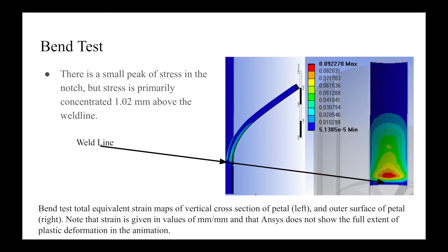The next slide shows two maps: one of the total strain on the outer surface of the petal after it has been bent over the rod, shown on the right, and the total strain going down a vertical cross-section of the petal, shown on the left. As can be seen, stress is concentrated at a point around one millimeter above the weld line on the outer surface. Furthermore, the stress inside the petal decreases towards the middle, around 0.25 millimeters into the tube, showing that stress is not evenly distributed on the inside but is concentrated on the inside and outside surfaces.